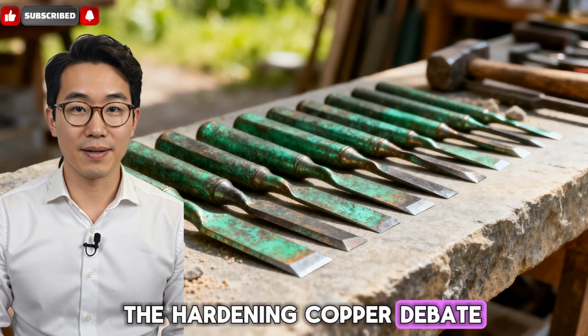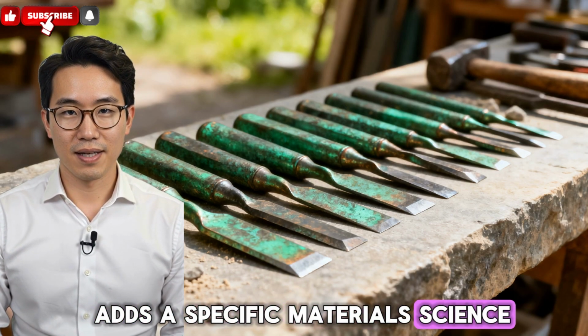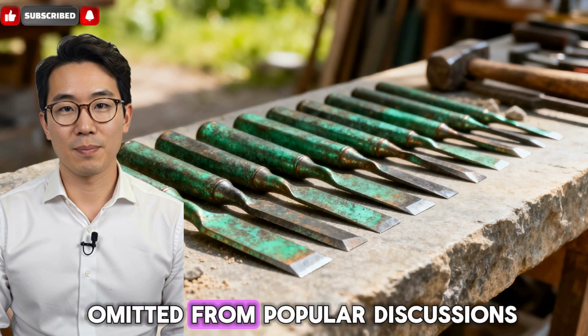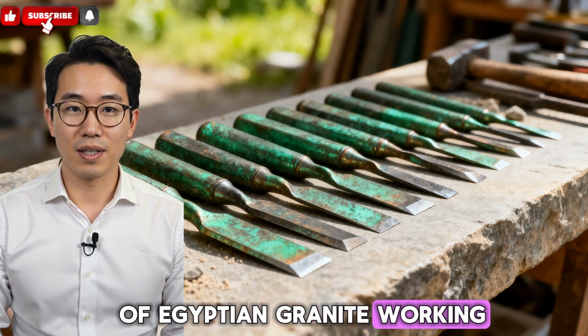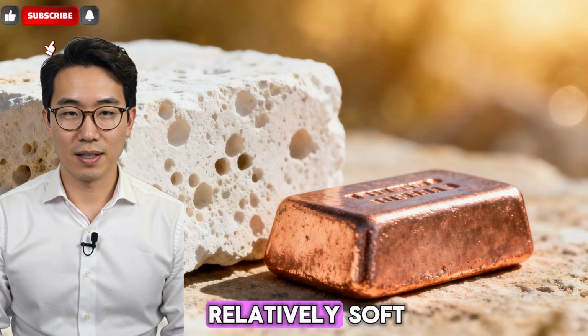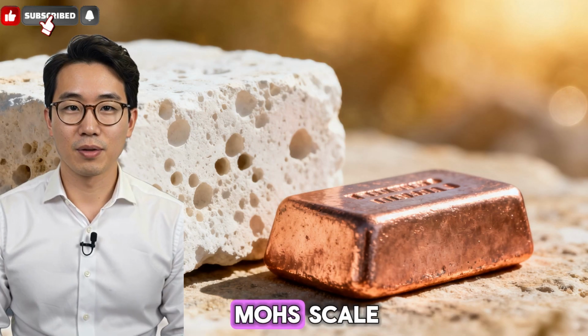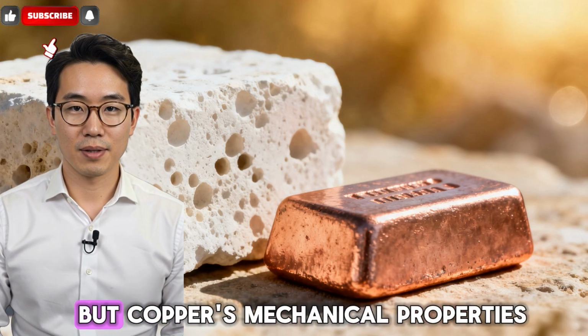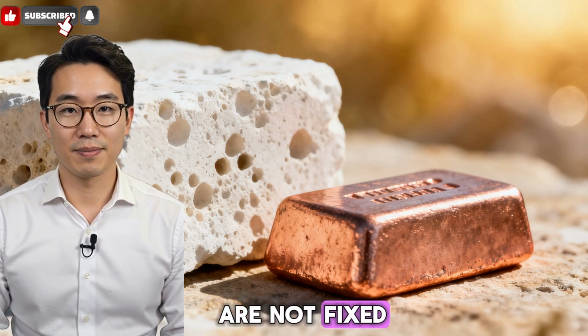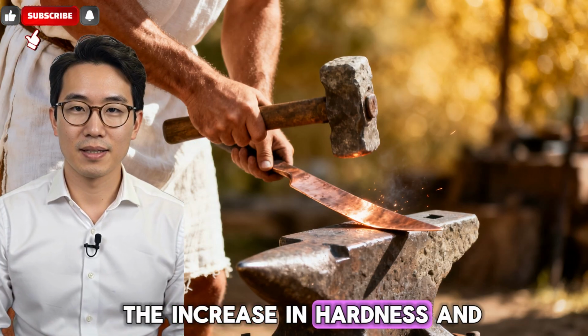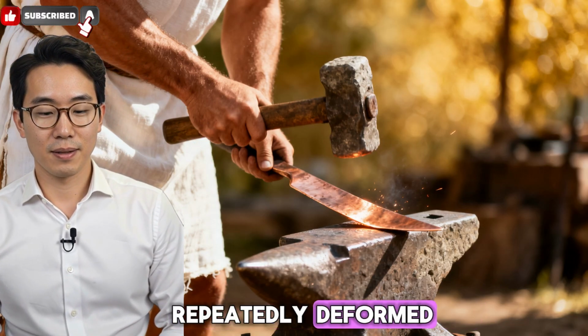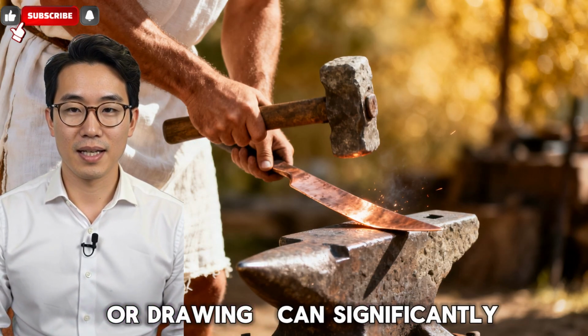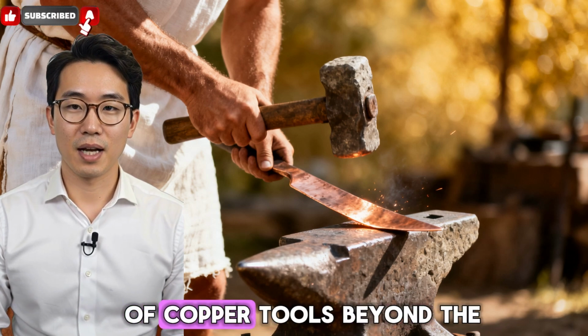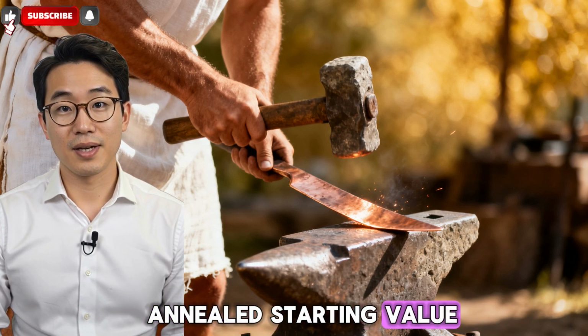The hardening copper debate adds a specific materials science dimension that is frequently omitted from popular discussions of Egyptian granite working. Modern pure copper is relatively soft, approximately 3 on the Mohs scale, comparable to limestone, but copper's mechanical properties are not fixed. Work hardening, the increase in hardness and strength that occurs when copper is repeatedly deformed, as by hammering or drawing, can significantly increase the hardness of copper tools beyond the annealed starting value.